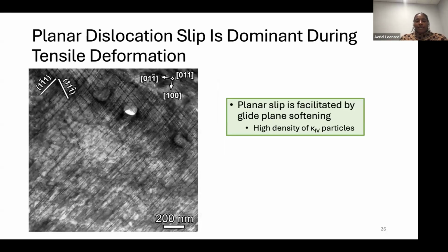Another thing we noticed at the higher strains is that planar slip is dominant, right? We do not see tons of cross slip. And I should say, in the traditional sense of cross slip, we don't see a lot of it. Planar slip is really being facilitated by glide plane softening. So you could imagine one partial goes through, it destroys the order, which makes it easier for other dislocations to follow along. And so you get an easy path for slip throughout your matrix.